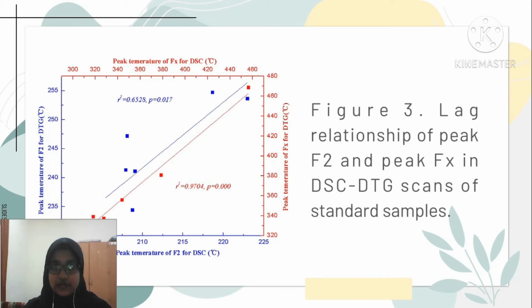Next, Figure 3 shows the lag relationship of peak F2 and peak Fx in DSC and DTG scans of standard samples. To conclude, there was no obvious loss of mass peak and a lesser rate of loss of mass in the F1 peak at 93 to 110 Celsius, suggesting that peak F1 represents a melting process, which is consistent with the DSC result. Peak F2 represents a recombination process of endothermic melting in the first half and endothermic degradation in the latter half, while peak F3 represents a stable stage before the strong exothermic degradation, but not an endothermic loss of mass. Lastly, most samples with peak F5 showed larger loss of mass peaks at 460 Celsius, coinciding with the behavior of lignin.